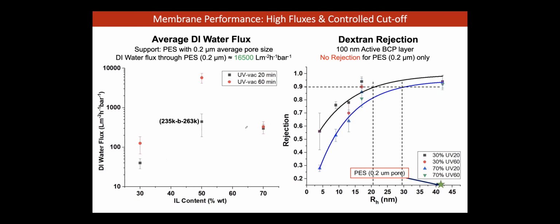And you can have different UV conditions, but this kind of non-linear profile doesn't change, non-monotonic, I should say. So one has to figure out the reason for this maximum. But it is clearly, in my mind, the pore density times the pore size. You can have large pores, but for sure you're decreasing pore density, right? So where's the optimum? So that's one, there's a non-monotonic behavior. And then if you look at rejection, and these are the pores of different size created with different UV conditions and ionic liquid, the black curve is at the top compared to the blue, and this is rejection.